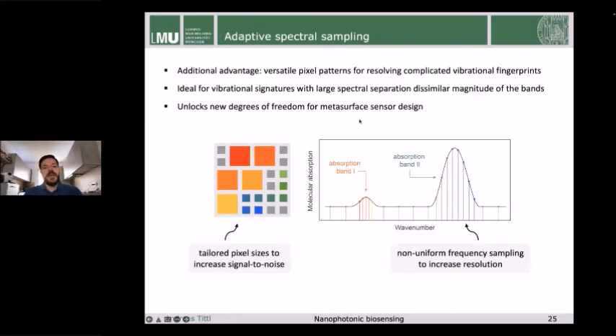And on top of that, we actually have significant advantages with this pixelated approach in the technological application. If you consider you have a sample with two absorption bands that are spectrally quite separate and that have different intensities, you can actually tailor your metasurface by using pixels that are larger, where you have just a small signal from your analyte, and smaller, where you have a large signal, to get a uniform signal to noise. And you can also tailor the frequency steps to detect only at these absorption bands of interest.